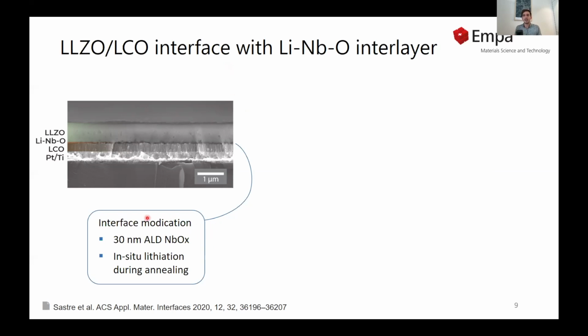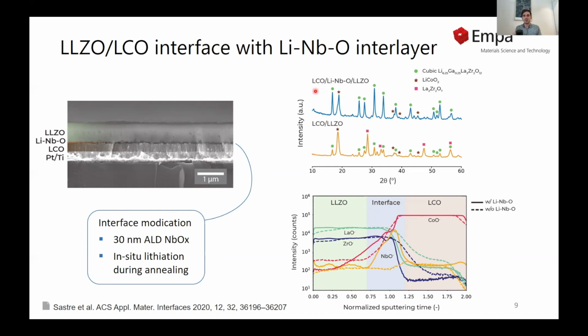We introduced a 30 nanometer atomic layer deposited niobium oxide interlayer, which then is in situ lithiated during the co-annealing process. With this interface modification, we were able to obtain pure LCO-LLZO phase without any secondary phase, as we can see here in this XRD plot, in comparison to the already shown bare LCO-LLZO interface. Also, looking at the elemental distribution acquired by TOF-SIMS, we observed that the interface is capable of blocking the interdiffusion of lanthanum and zirconium into the cathode and cobalt into the electrolyte.